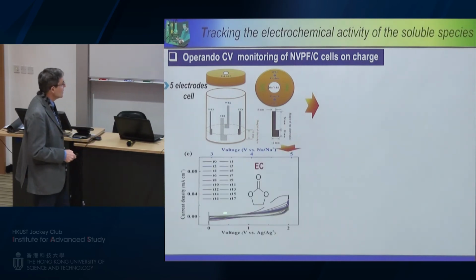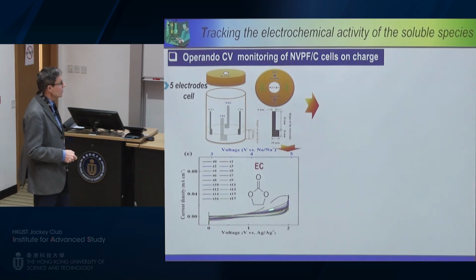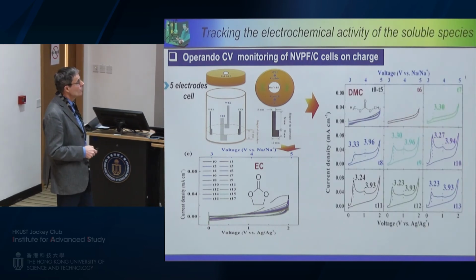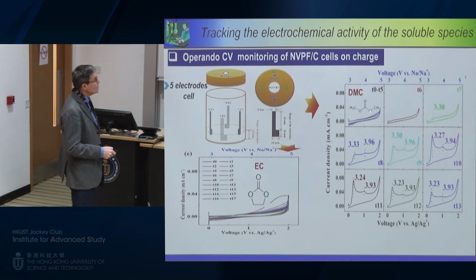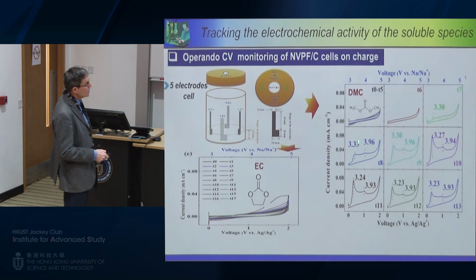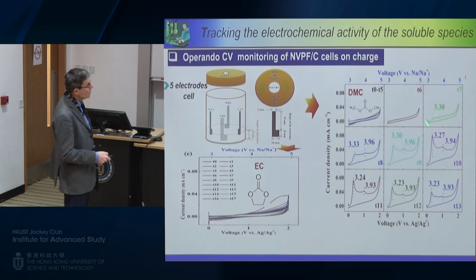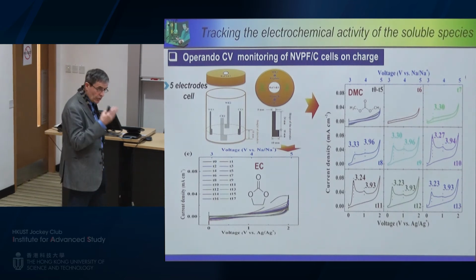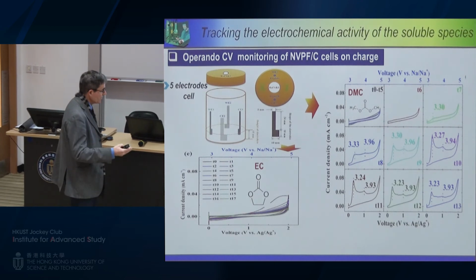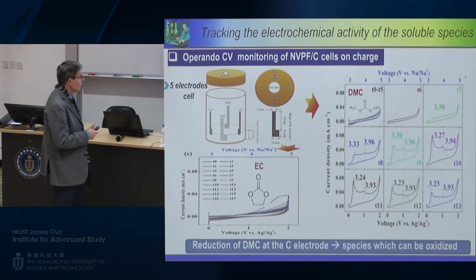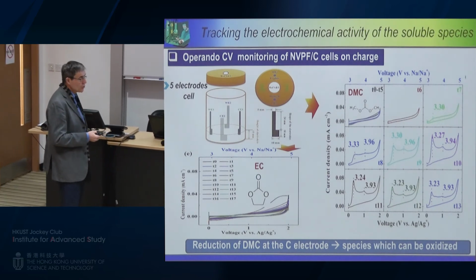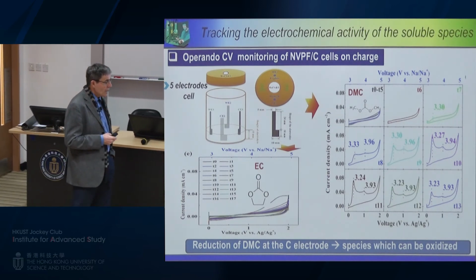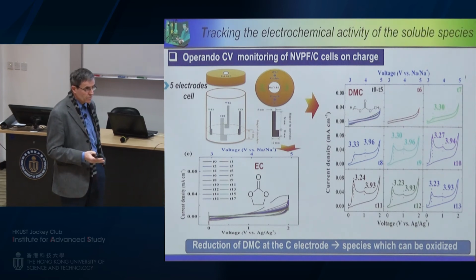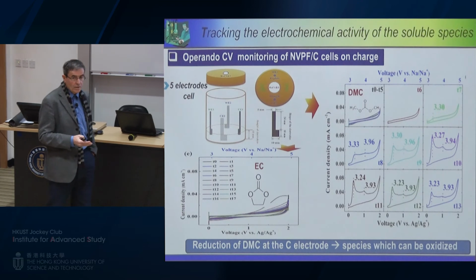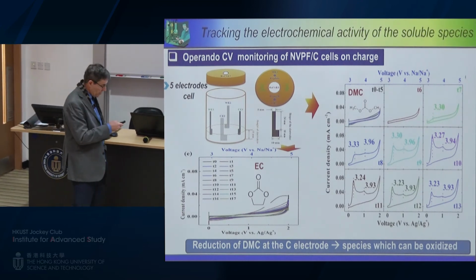In the case of EC, as you can see, there is not too much activity. The curves are featureless. While now, when we move to DMC, look here. Suddenly, these two peaks pop out, increase, and then decrease later. So it means now that we are generating species that can be oxidized. This is quite interesting, because this indicates that we have a reduction of DMC at the carbon electrode, and this releases species which can be oxidized. Now, of course, the question is, what are these species, and what is the origin of these species?